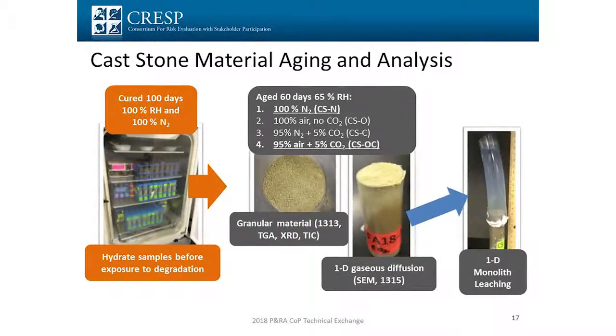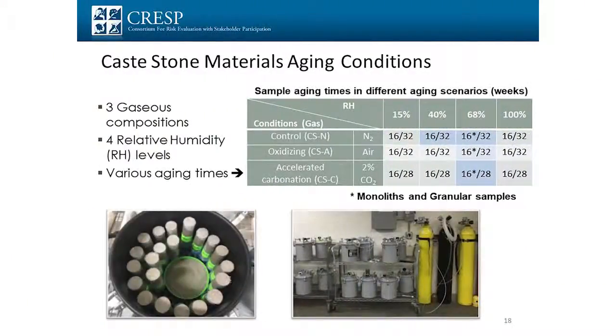So again, age 60 days, looking at doing thermogravimetric analysis, method 1313, which is a pH dependent test, XRD, and total inorganic carbon. We're doing SEM on these. We're doing the monolith testing for mass transport. So we're doing a suite of tests to try to characterize the behavior of these materials and the effects of carbonation and oxidation.